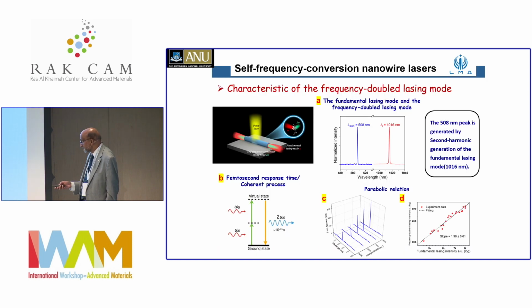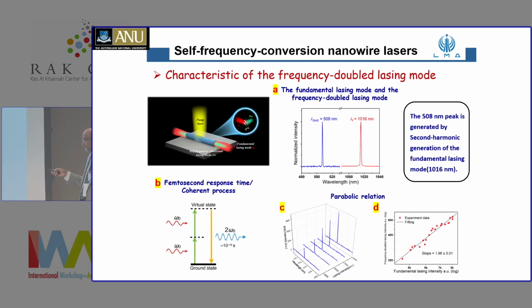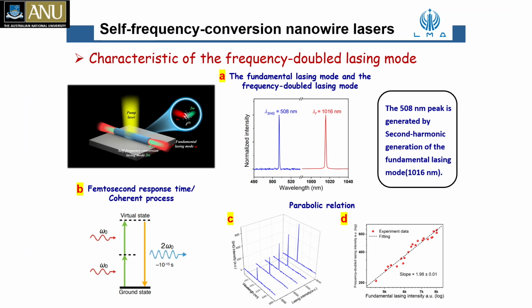So if you take this nanowire, excite it with a laser pulse and look at the light emission, the fundamental mode is emitting at 1016 nanometers, and the second order mode is emitting at 508 nanometers, and that's what you would expect. That means the same nanowire can now be used to make infrared light emission as well as visible light emission. For lots of applications, people want dual wavelength lasers, also for digital printing and other things, and we're able to use the same nanowire to generate both colors of light. That really opens up a lot of opportunities for us.